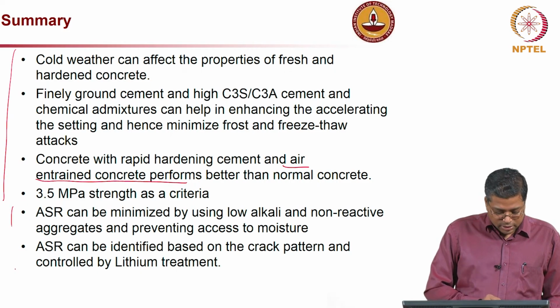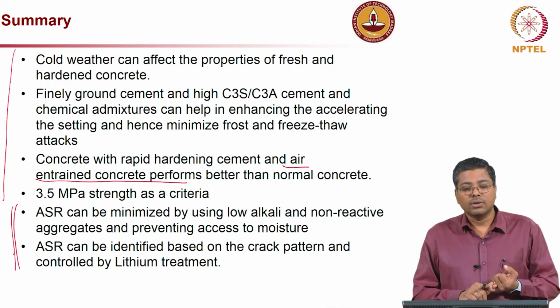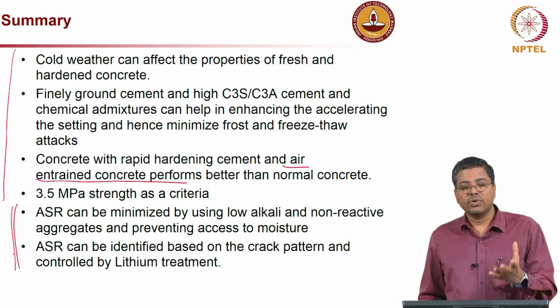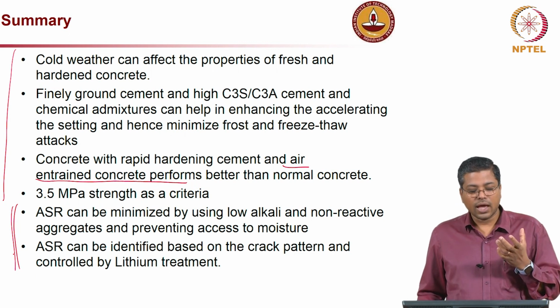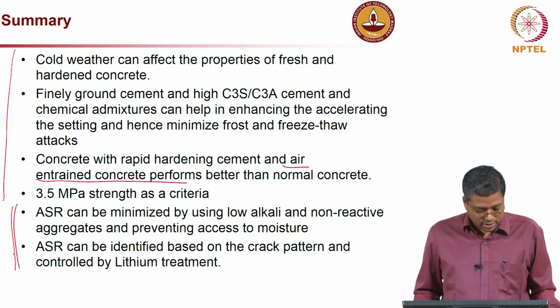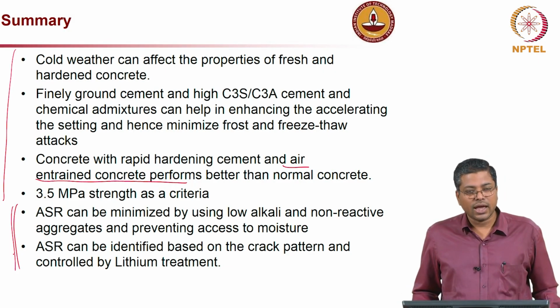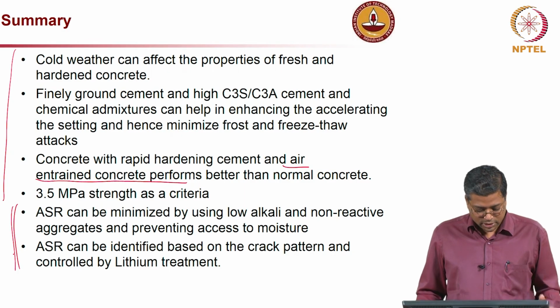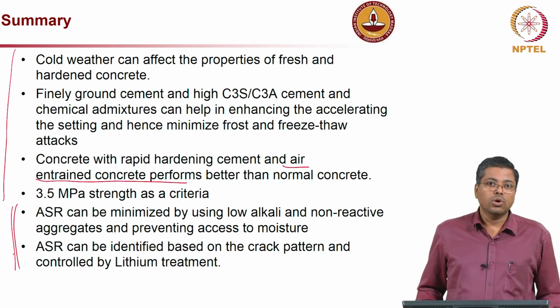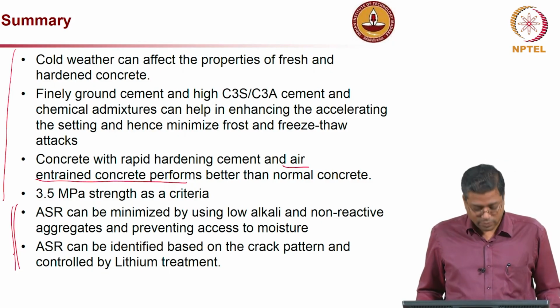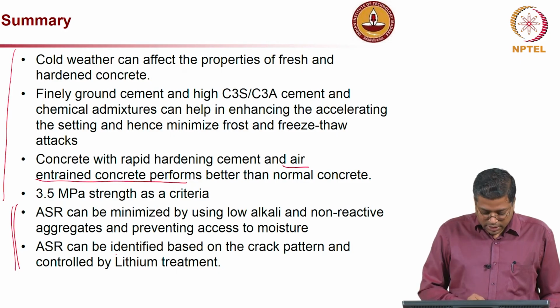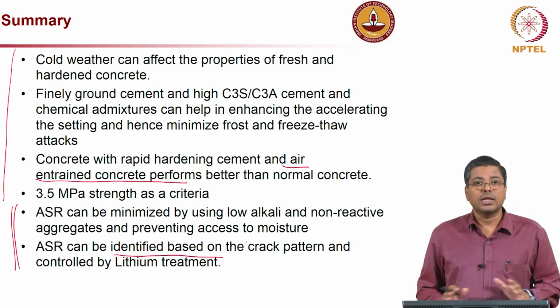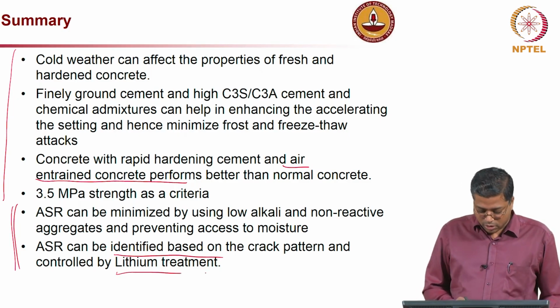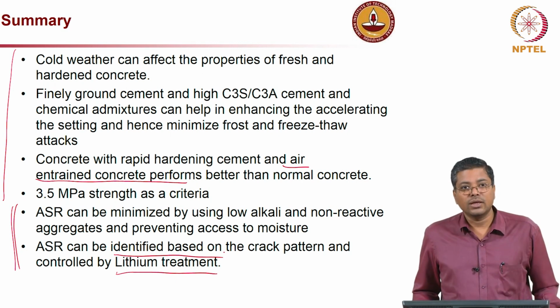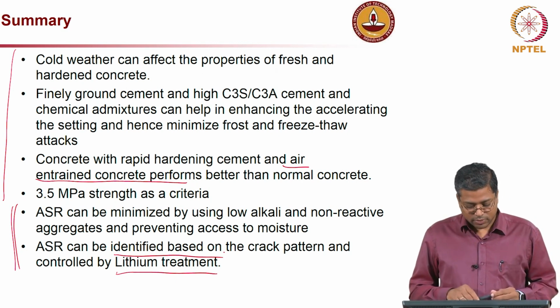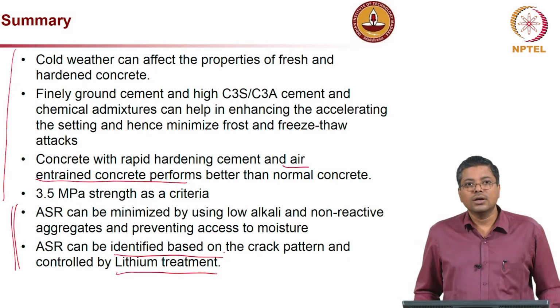And in terms of ASR, we saw that ASR is basically the reaction between the alkali content in the cement and the reactive aggregates, and different types of aggregate can have different levels of reactivity, and you have to probably choose low reactive aggregates, so that such ASR related problems will not happen. And ASR can be identified based on the crack pattern, typically map cracking, and it can be controlled by lithium treatment. Also this is not very easy to do, it is a very time intensive and expensive method.